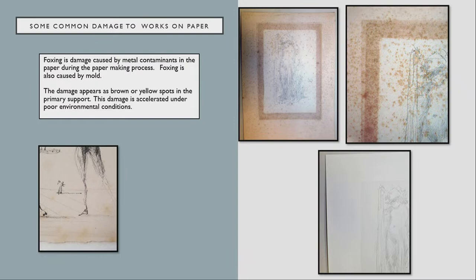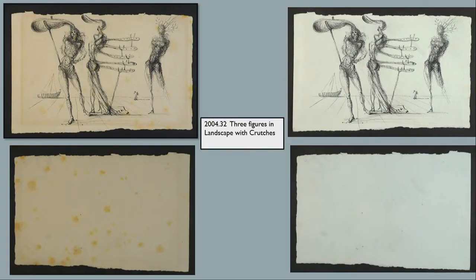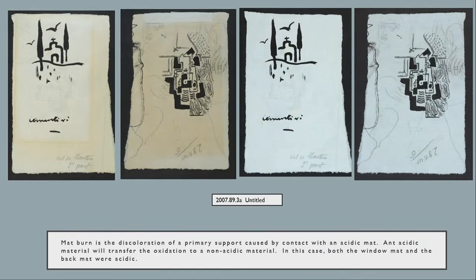There's a close-up there, and then after conservation, the foxing was removed, and it can be removed. Here's a piece of a Dalí piece, which had foxing, other forms of oxidation. That overall discoloration is from acidity, and then the spottiness is from foxing. Both of them were able to be resolved, fortunately.